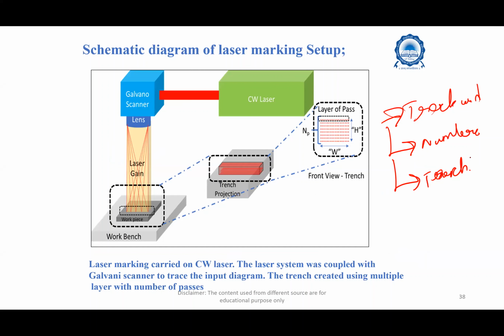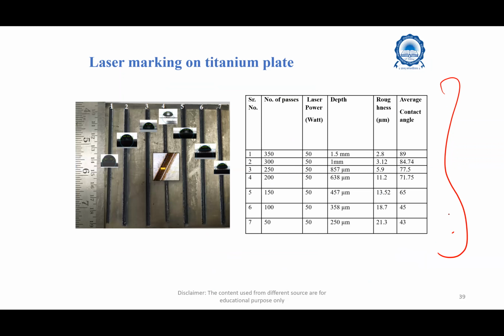And when I try to focus my arc, I can fabricate thin sections out of it. With this as an idea, we started our work by changing the different process parameters. These are the different process parameters which we employed for creating a marking on the titanium plate: the number of passes and the laser power. We studied the depth and the roughness, and using contact angle measurement we were trying to investigate the average contact angle. Basically, the idea behind this is that not only are we trying to concentrate the arc, we are also trying to focus on the wettability of the droplet which falls on the surface, and with respect to that we were trying to study the overall behavior of the system and take care of the track width coming out of it. So in this case, the roughness of the substrate basically plays a major role.